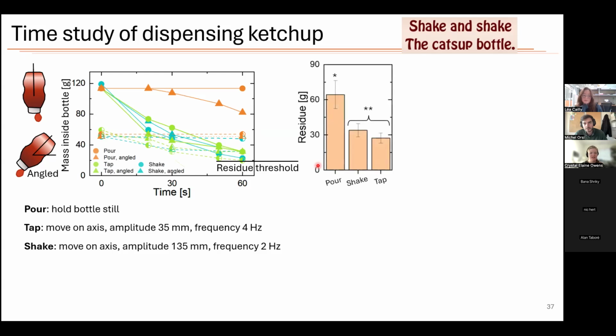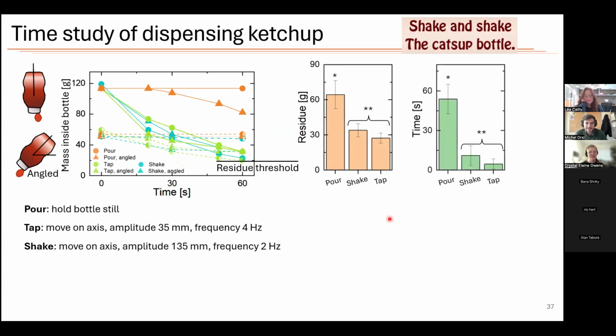So we collected all of our data together to see, according to what protocol you use, you will always leave more residue, statistically more residue, if you simply pour rather than if you shake or you tap. So it is definitely better to get the ketchup out if you do shake it, rather than what they showed in the commercials where you just kind of hold the bottle. And the time it takes the first bit of ketchup to come out is also significantly faster, even more dramatically so, when you shake and when you tap, rather than when you just wait.